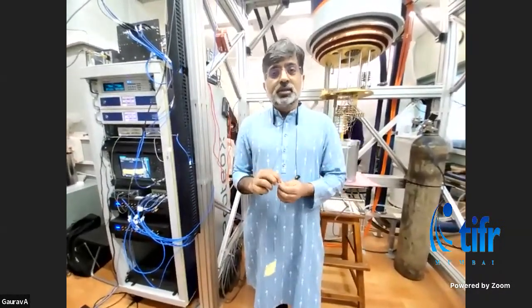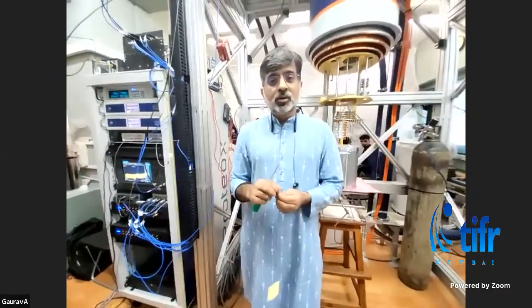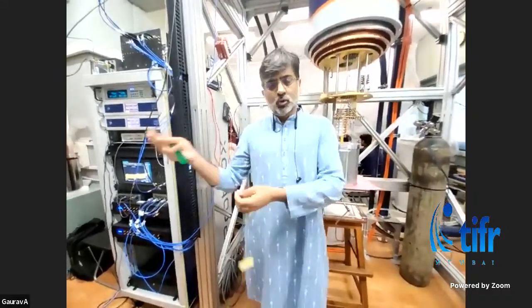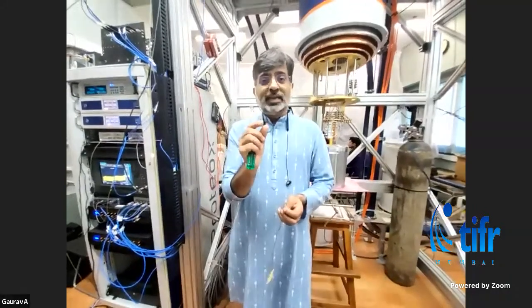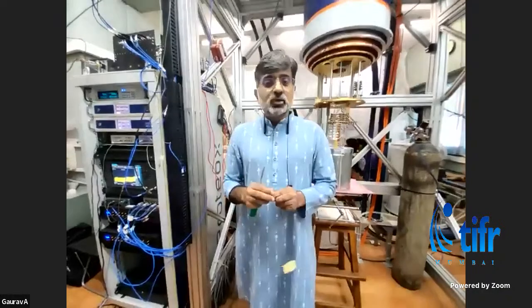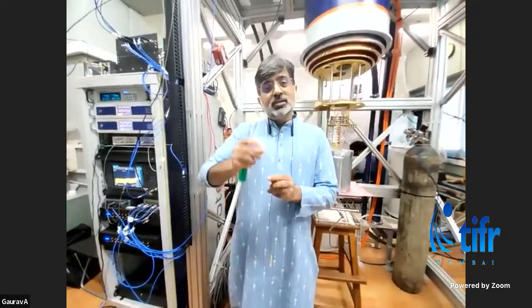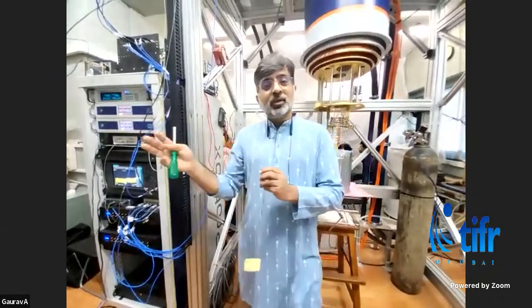And what is really important is how quickly you can do the operation. So you saw this pi pulse calibration. He talked about 70 nanoseconds. That's actually slow. You can make it faster, to about 5 or 10 nanoseconds. And that's a measure of how long it takes to do one operation. A 2-qubit gate might take about 100 nanoseconds or so. And then you can see how many such 100 nanosecond operations you can fit over this time scale of about 20 microseconds or so.